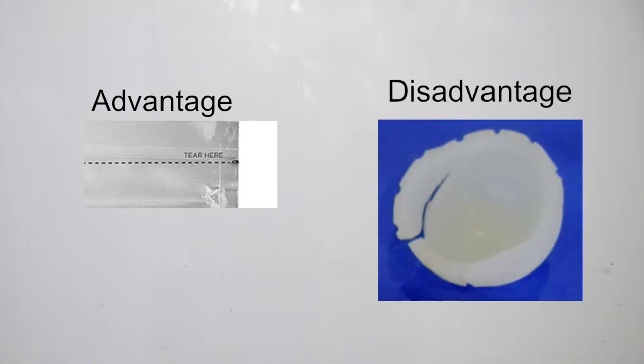In this case, the fracture behavior of the polymer is an advantage. One example of where this is a disadvantage is in some shoulder joint replacements. In some cases, the designs will have small notches that can act just like the small cut in a plastic bag. If a big enough force is applied near the notch, it can help start a crack that will travel through the implant and cause it to break.